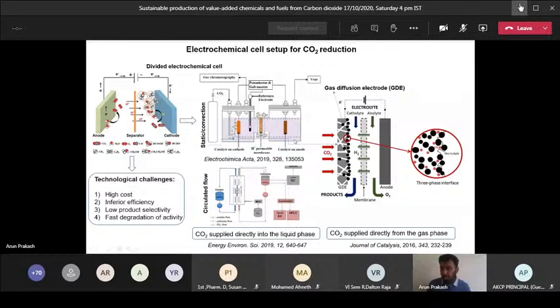And what are the other factors influencing the reaction kinetics? When you have an electrode, you have your electrolyte and the diffusion layer. So the diffusion layer is from the bulk to your electrode interface. There will be a concentration gradient developing. For instance, the CO2 in the bulk solution will be much higher, but the CO2 near your electrode surface will be very less. So always, whether gas or potential or everything, will move from the higher concentration or higher potential region to the lower.